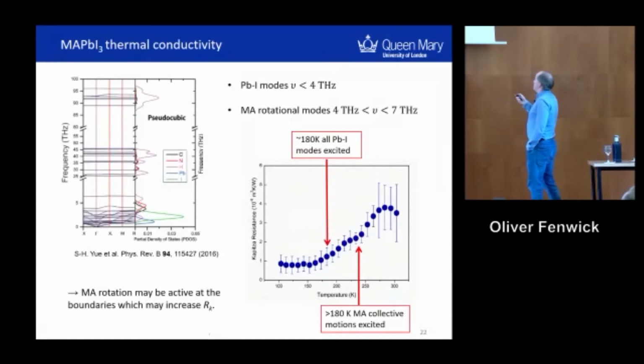What we did notice is that the lead iodide cages have phonon modes that are less than 4 terahertz. They're plotted down at the bottom here in yellow and blue. The methyl ammonium modes have frequencies that are slightly higher. And so at about 180 Kelvin or so, we'd have expected all of the lead iodide modes to have been excited already, and then the methyl ammonium modes start kicking in after that. So we're sort of hypothesizing that something to do with the methyl ammonium is happening at grain boundaries that's maybe causing that increase in Kapitsa resistance, but I'd say it's a little bit uncertain. I've got correlation rather than solid evidence there.